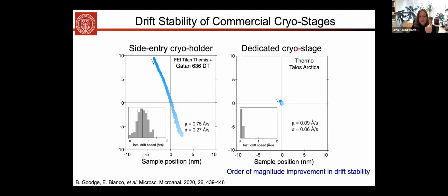Why are we not using it? In fact, this is our Talos Arctica here at Cornell. Well, the problem with this instrument is that it lacks dual axis tilt capabilities. So in a crystal, compared to a biological molecule, we need to be able to orient our crystal onto a crystallographic zone axis. And that means that we need two tilts or a tilt and rotation, or any combination. And that currently does not exist in biological dedicated cryo instruments. And so we are currently limited by the drift with our side entry holders.